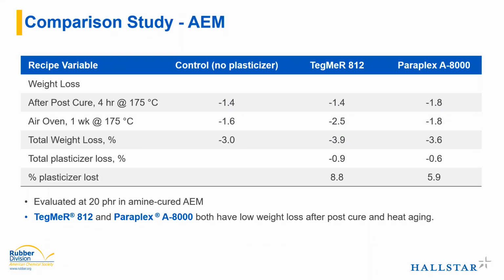And then just one quick last thing here, looking at acrylics, because that's another common application for a lot of esters. A lot of times acrylics don't like to use very much plasticizer, and that's understandable because they tend to be very high performing and they don't want to sacrifice any of that performance by diluting with a plasticizer. But in this case, we're looking at a control with no plasticizer whatsoever versus the Tegmer mentioned here. That's the same material I mentioned with the HNBR.